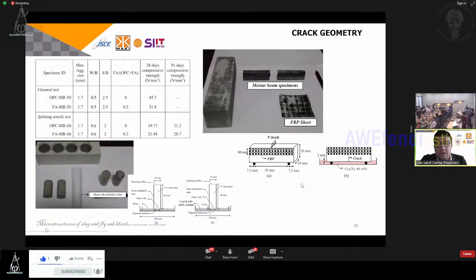And then for the crack geometry, again here we prepare two types of specimen. One for conventional OPC, and the second one using fly ash. Two types of crack: first, generated by flexural load, and the last one generated by splitting tensile load. For the flexural specimen, we apply oven dry treatment, and for the splitting test, we apply saturated condition. The specimen was immersed in water for at least 24 hours before the diffusion test. So in this case, we will have absorptivity, and the last one, we will have diffusivity.